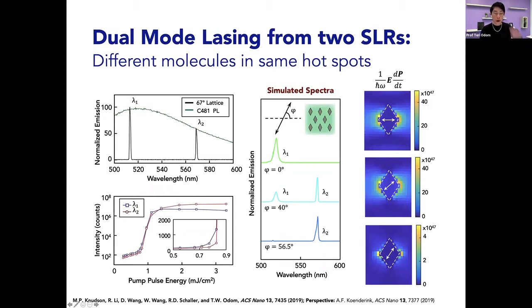So we can use this system to test for lasing, and we're able to achieve dual mode lasing. This is the gain bandwidth, the C481. This is the photoluminescence, and these are the wavelengths of the lasing modes that correspond to the SLR wavelengths. And you can see that it spans pretty well the whole bandwidth. We look at the light curves, thresholds are about the same, which would make sense. And then this is the simulated spectra that I showed you earlier. And again, this is the stimulated emission map. And so you can see that regardless of whether we're evaluating lasing at shorter wavelengths or at longer wavelengths, and again, these are a function of polarization, the hotspots are always at the same locations. So you have different molecules, but in the same hotspots, that can contribute to these different colors, which I think is quite interesting and unique to think about engineering at the unit level and breaking symmetry in order to access these types of properties.